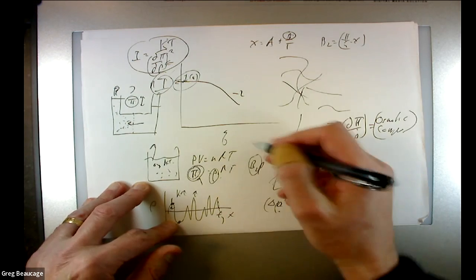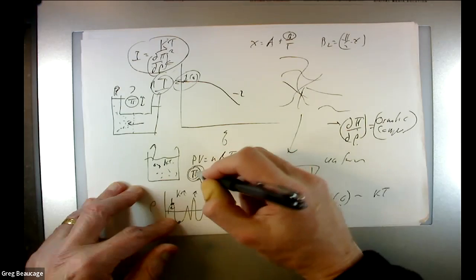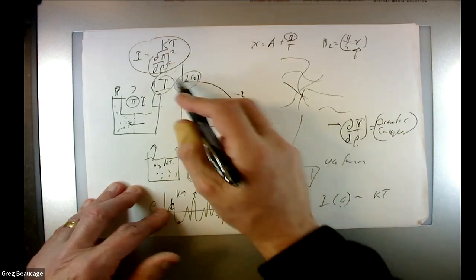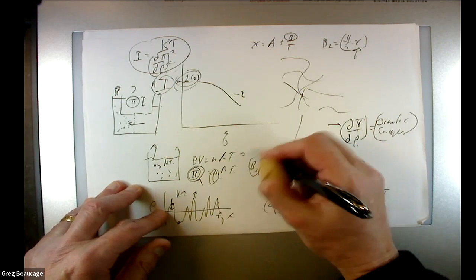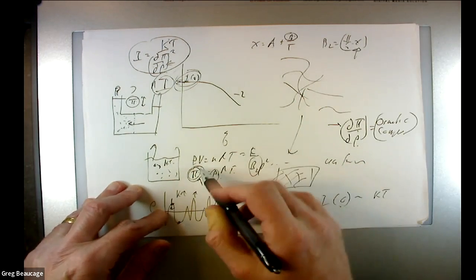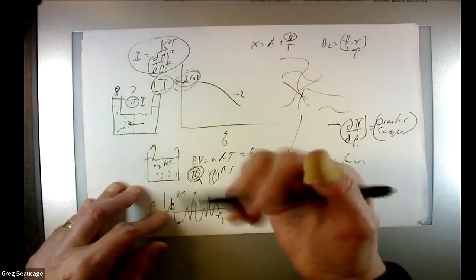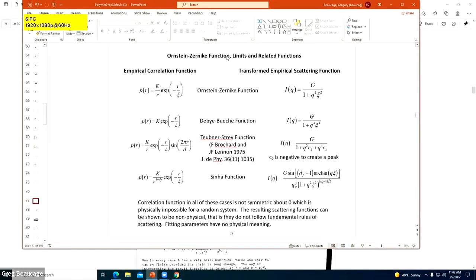And if you can write that B2 is 1/2 minus chi, then you can write an expression for the osmotic compressibility in terms of chi, in fact, in terms of the free energy for the chain, so you can calculate what this I naught is in terms of chi. Right? Because this PV is the energy. We have an expression for the energy of the chain in the solution, the Flory-Huggins equation. So you can calculate the osmotic compressibility, you calculate the I naught. So it's a way to measure chi. The details of it are kind of tedious, but that's the idea of it, right?